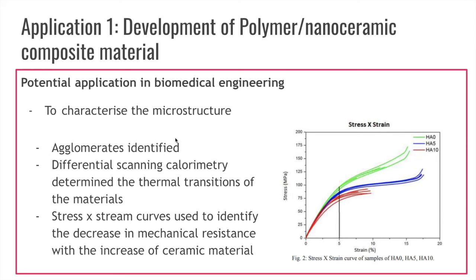Agglomerates were identified in the SEM images, which indicates that the extrusion process during the development of the materials wasn't efficient in homogenizing. Differential scanning calorimetry determined the thermal transition of the materials, and a trend was identified where the increased percentage of the ceramic material reduced the crystallization temperature. Stress-strain curves were used to identify the decrease in mechanical resistance with the increase of the percentage of the ceramic material. It was concluded that further research into the material's degradation was needed.